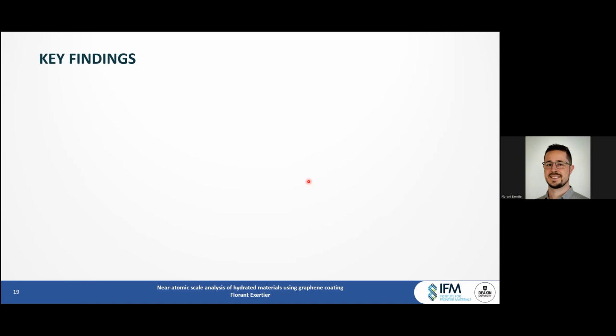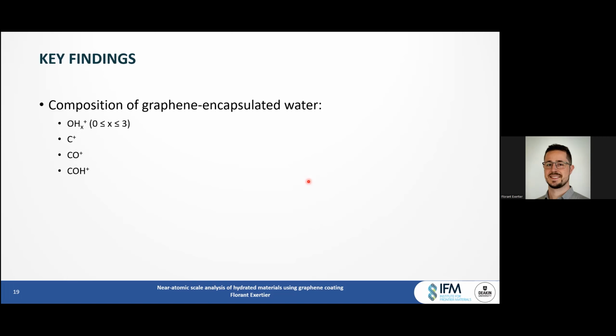So the key findings of this part of the study on water is that we were able to single out the composition of graphene encapsulated water, which was essentially OHx+ ions with x between 0 and 3, and carbon with C+, CO+, COH+ coming from, well, the graphene. But also we realized that these three species were actually in reduced amounts after cryo-FIB removal.